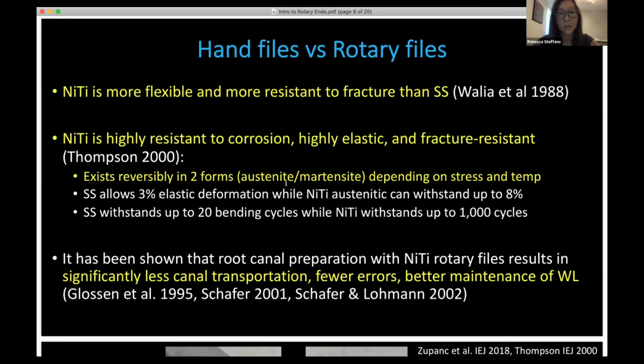Again, looking at a comparison between the stainless steel hand files versus these nickel titanium rotary files, the NiTi has been found to be more flexible and more resistant to fracture compared with stainless steel. The NiTi is highly resistant to corrosion, highly elastic and fracture resistant. We'll get into the properties of the nickel titanium files. They exist reversibly in 2 forms, austenite and martensite, depending on the stress on the file and the temperature. Studies have shown that while stainless steel allows a 3% elastic deformation, nickel titanium in its austenitic phase can withstand up to 8%. And stainless steel withstands up to maybe 20 bending cycles, while nickel titanium up to 1,000.